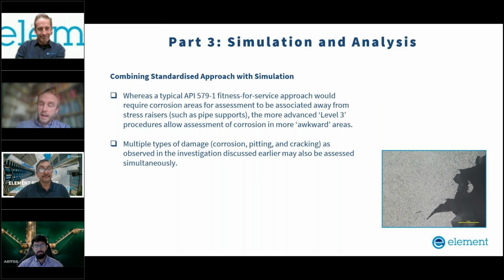So as I've mentioned, the typical fitness for service procedures, such as in API 579, which is one of the sort of highly recognized standardized international procedures for fitness for service, would require that numerical simulation is carried out for complex configurations such as this, where you've got complex geometries like areas of damage sitting underneath pipe supports, where there are stress concentrations, you've got complicated regions of damage and so on. So these, what I term level 3 type procedures, are really useful in this type of analysis that we carried out.